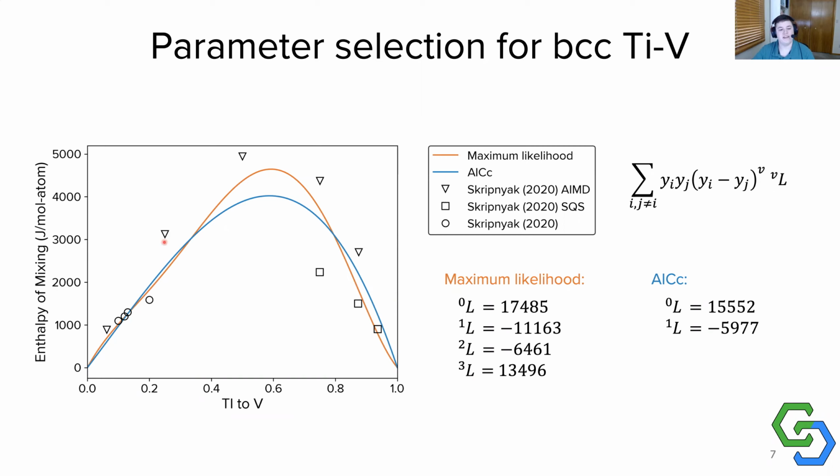But as you can see with this data, these 4 parameters aren't really giving us a whole lot of information or a very good fit for the number of parameters we're paying. So maybe using 2 parameters, which the AICc selects for us, would be a better choice. You can see just visually that the lower number of parameters qualitatively gives just as good a fit to the data here as the 4 parameters.